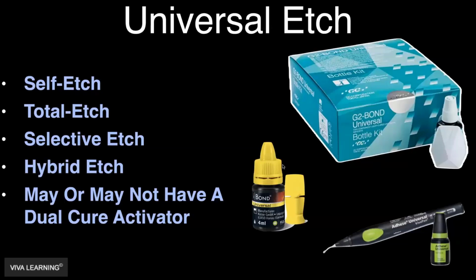Kind of a classic example of that for me is one of the few things in my practice today that I still truly total etch, which means that I cover the entire preparation of the tooth with phosphoric acid, and I go 25 to 30 seconds, would be anterior ceramic veneers, where my prep is predominantly in enamel. Most of my other clinical procedures, I'm not going to want to put phosphoric acid on dentin for 25 or 30 seconds, so I wouldn't use a true total etch technique. And I can have one of these universal or eighth generation adhesives in my practice, and I don't have to think about what my assistant put out. I can use it in whatever technique that I want.